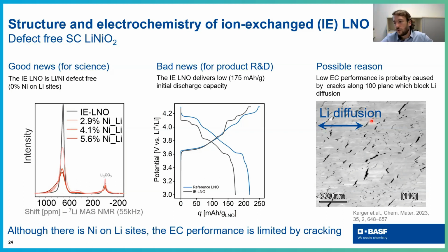And if you then remember that sodium nickel oxide has another space group, it's monoclinic, and our LNO is rhombohedral, then there is a change in the lattice, and this change or strain vector is actually oriented in this direction, and in this direction we are experiencing the cracking. So the ion exchange leads unfortunately to such a strain, and then we have a lot of cracking in our material, which limits our electrochemical performance.